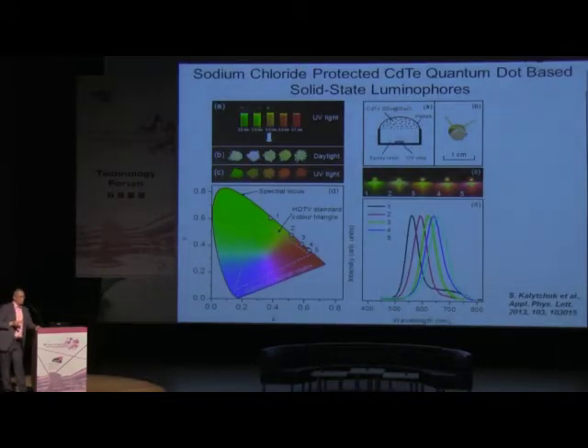So now let me go to real devices, to LEDs. One example about quantum dot-based devices, again cadmium telluride, and in that case what we did, we made them again in solution like we always produce our samples. We mixed them with sodium chloride, which is just a normal salt. If you go to a canteen, you get salty food. This is because of this sodium chloride salt.